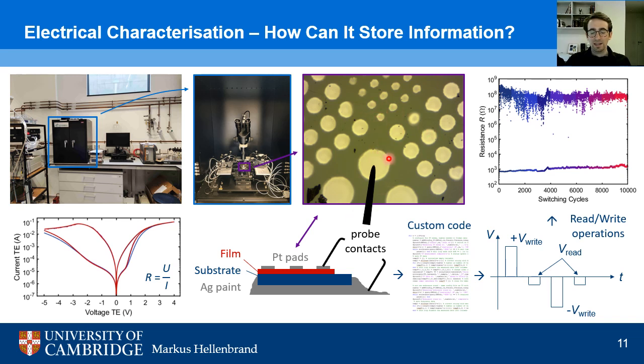It is just a metal, and if we look at the cross section, going into the screen, so to say, then we have the device structure that I pointed out before. So we have one electrode on the top, which is denoted by platinum pads here. In red, we have our oxide, which actually does the switching between two information states, and then we have the bottom contact, which here is the substrate. But in general, remember, we just have three different components: one top electrode, the oxide, and one bottom electrode.